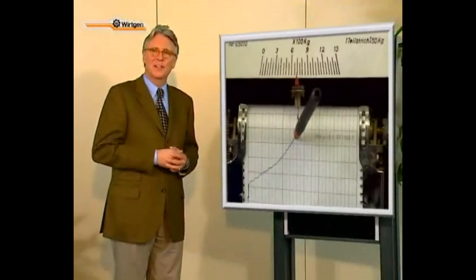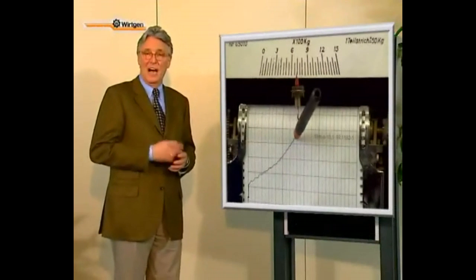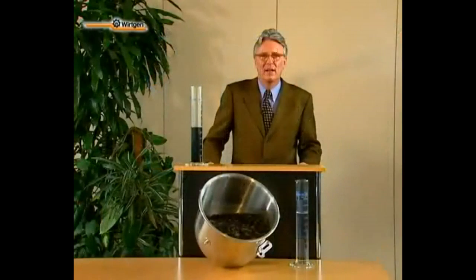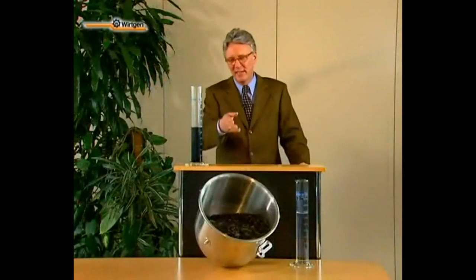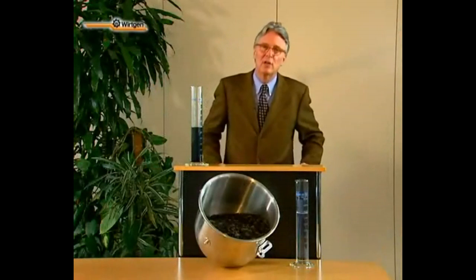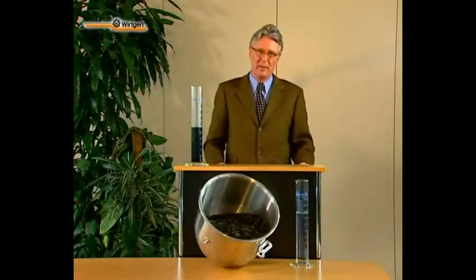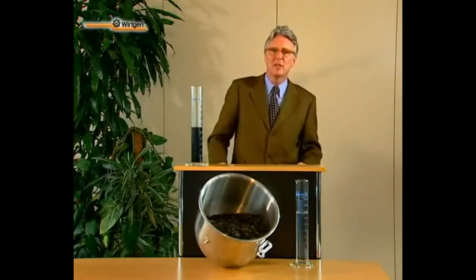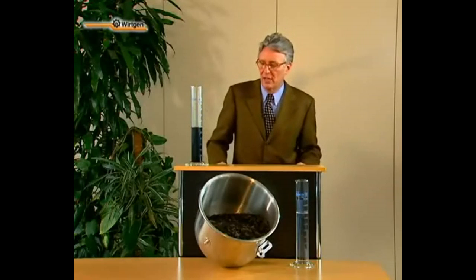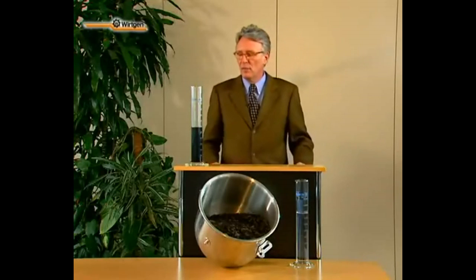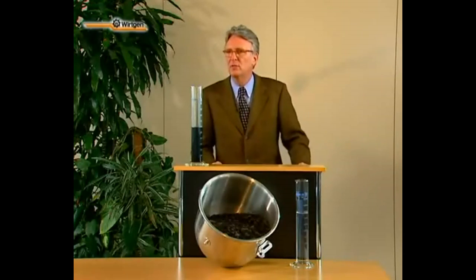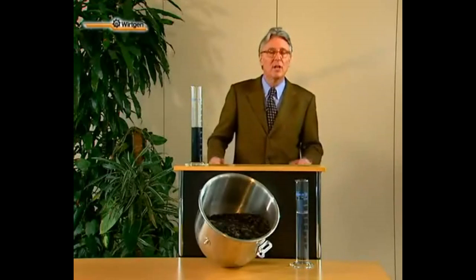There's one important question that we haven't answered for you yet. How does this foamed bitumen actually work as a binding agent? In our example, milled material is the source material, consisting of 15% filler by mass. 4% of water are added to achieve optimum compaction moisture, and 3% of bitumen in the form of foamed bitumen are sprayed and subsequently mixed into this material in the manner already shown.